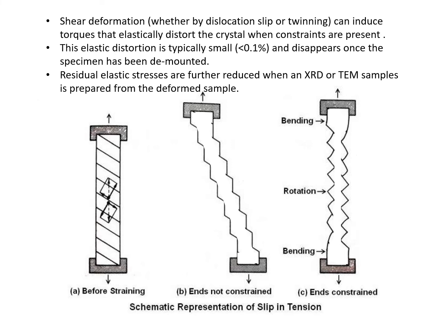If you look at a simple tensile test, and we're talking about dislocation slip, let's say we have these slip planes here, then what happens when you deform the material, and if you have a large amount of slip, the load line will actually get shifted over to this direction. But the load frame is going to want to pull in this direction along this load line. So in order to conform with the tensile machine, the sample has to be bent back into register with the load line.